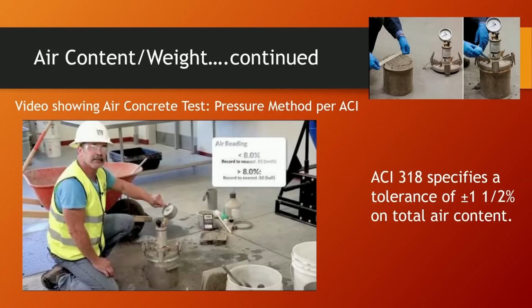When we depress it, we're going to strike the sides of the air meter. That's a plural word, sides. You need to strike the pot a minimum of 2 times. After striking the pot, tap the back of the gauge until the needle stabilizes. Continue to hold the main air valve open until that needle stabilizes. Once the needle is stabilized, you can release the valve and get your reading to the nearest 1/10. Anything over 8%, you'll get to the nearest 0.5%. So it'll be 8, 8.5, 9, 9.5.